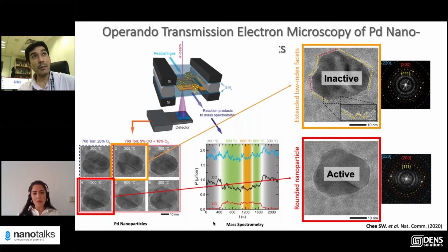But in many cases, there is no detectable oxide. In this specific case, we think it's some carbonaceous material that might be building up on the surface because it was really amorphous. When you do the experiment with, for example, rhodium, you see clearly oxide formation on the surface.